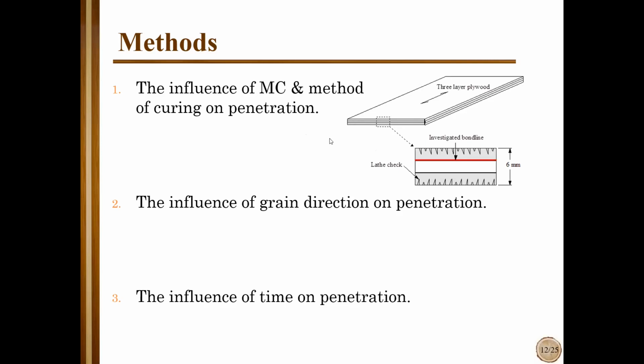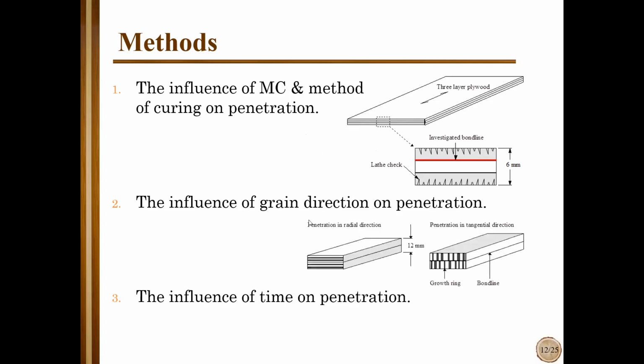So at 5 different moisture levels. The second one focused on the influence of grain direction on penetration, either radial direction or tangential direction of penetration. And the last one was the influence of time on penetration, I could say open assembly time. We applied adhesive on the surface and took samples after 1 minute, 2 minutes, and so on.